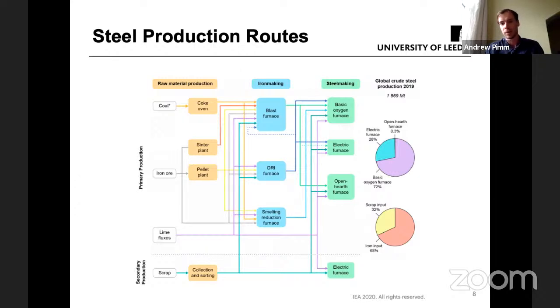You then, to produce steel, need to reduce the carbon, because you're left with a high level of carbon, and also get rid of a small percentage of impurities. So you do that using oxygen, and then potentially also add other elements for producing certain alloys. So yeah, there's the blast furnace. There's also DRI, which is direct reduction of iron, which is a different type of furnace, which again I'll cover.